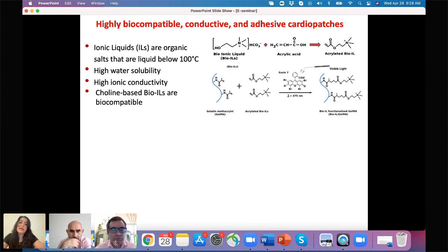So to address these problems, we look into a more biocompatible source to form this electroconductive hydrogel, and we use ionic liquids. Ionic liquids are organic salts that are liquid below 100 degrees. They have high water solubility. They have high ionic conductivity. And choline-based bio-ionic liquids are highly biocompatible. So in the lab, we use a bio-ionic liquid, and then through a one-step reaction with acrylic acid, we form acrylated bio-IL. And then this acrylated bio-IL can combine with any type of photocross-linkable biomaterial to form bio-IL functionalized hydrogel with tunable electroconductivity.